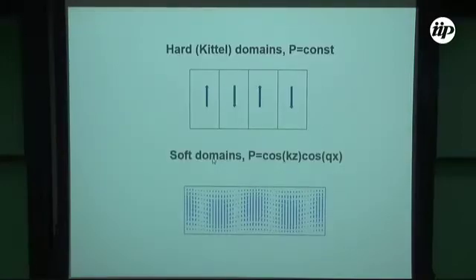So what is the difference between what we called hard domains, Kittel domains? We have polarization which is constant, and soft polarization, which really behaves like a sinusoidal profile in both directions. So first of all, this is the thickness of the film. Polarization changes periodically, but not sharply, quite softly, in the direction of the film.